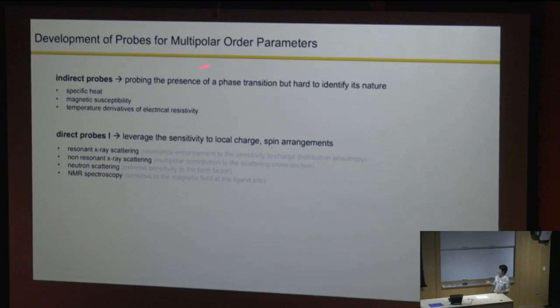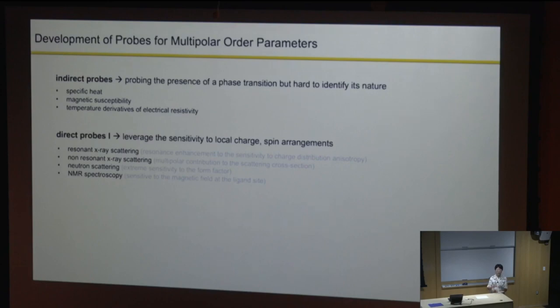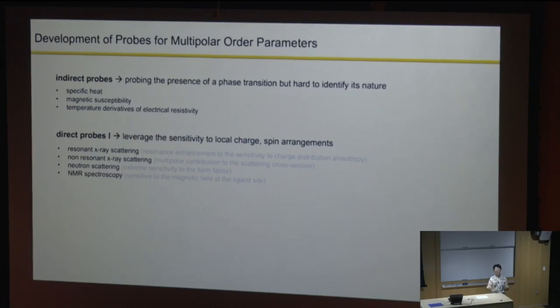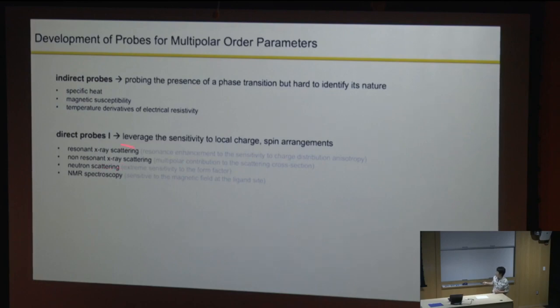The challenge with diffraction techniques is that you rely on the form factor to see the presence of this thing, and extracting the form factor requires measuring many peaks and caring about their relative sizes. Sometimes the relative sizes only change a tiny bit, making a conclusive remark challenging. These techniques include resonant X-ray, non-resonant X-ray, neutron, and NMR—all leveraging their local sensitivity.